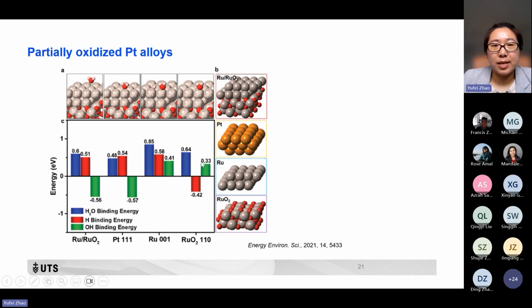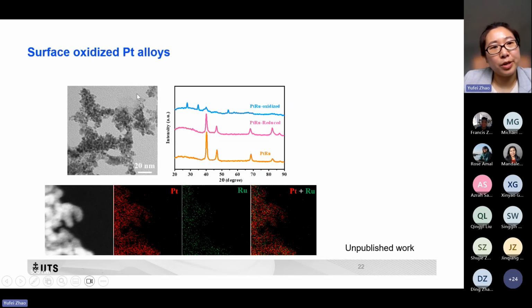They demonstrated that this reduced ruthenium oxide may make it easier to form a ruthenium and ruthenium oxide interface, and this interface can facilitate the HER. So for our case, we have prepared this platinum ruthenium alloy first, and then we try to reduce and oxidize this platinum ruthenium to obtain the reduced and oxidized samples, to investigate the influence of the valence state on the HER performance.